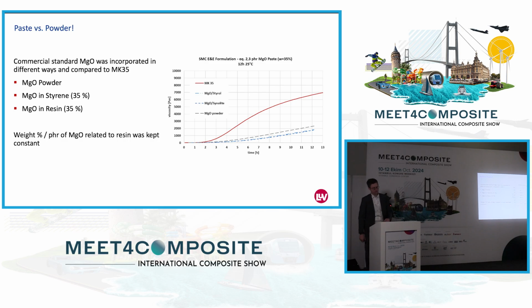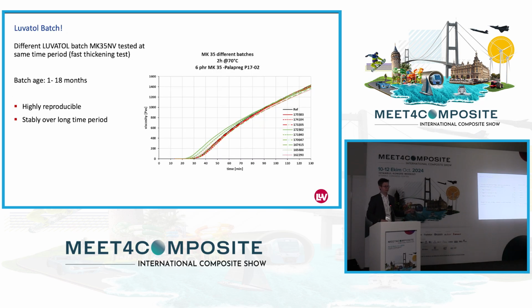And the difference we note is that even if you have MgO powder, the same grade, the same batch, sometimes because of the size of the MgO and also the shape of the MgO, the thickening even within one batch is totally different. And that's then our job. That's what we are doing with the MgO. We test all this and we make sure that you always have the same thickening effect.